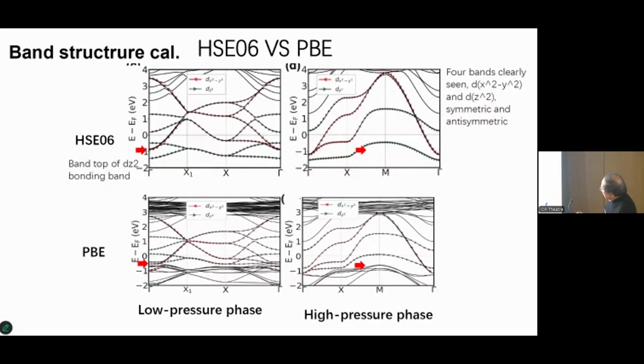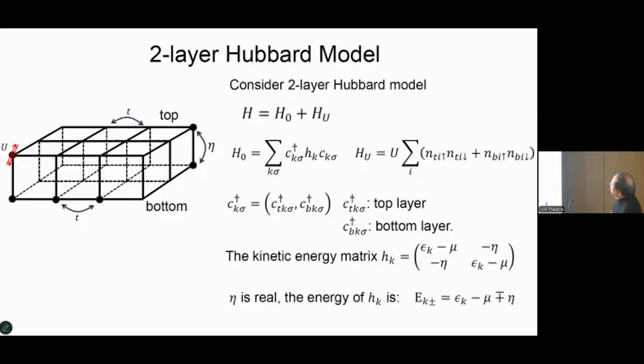So this is a lower pressure phase, and this is the high pressure phase. Let's look at the high pressure phase. I have a four-band here, you can see. Two are symmetric and two are anti-symmetric. It's a combination of the dx squared minus y squared and the dz squared. So the double layer structure gives you bonding and anti-bonding splitting of these bands, which are important. That just led us to study this two-layer Hubbard model.